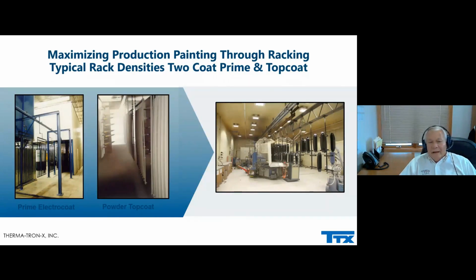Typical rack densities for two coat, as you see here, you see the parts. These are for luggage racks. Basically, it's an inverted conveyor to get the E-coat coming through, and you have as much density as you can. Why can't we coat these twice? Well, basically, a luggage rack has to be coated on both sides because it's going to see exterior ultraviolet rays on one side and moisture on the other. So they powder coat these and apply.